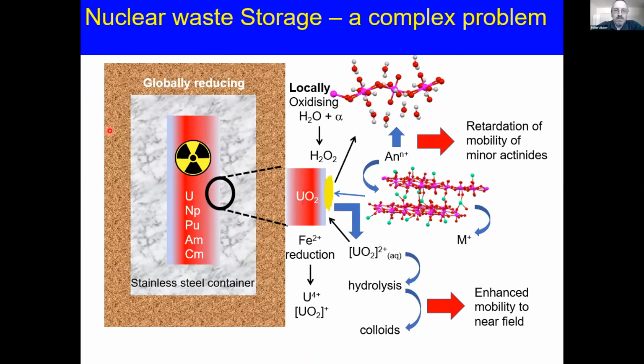The majority of waste in the UK, in Europe, is going to be in a globally reducing environment underground. And it's going to be probably stored in stainless steel containers with certain degrees of backfill. But over a long period of time, of course, water will eventually ingress into this. And because it's radioactive, this will generate hydrogen peroxide. Hydrogen peroxide is then a really good oxidizing agent to oxidize these complexes, which are generally in their +4 oxidation states as the oxides, to something that's more soluble, which can then move through the environment.